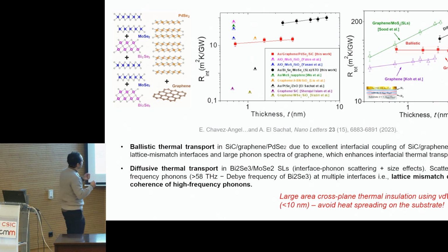Okay, so then you see that when this R total is not changing by increasing the thickness, the thermal resistance is not changing. This means that inside the material we don't have any internal scattering. So the phonons propagate without any scattering.